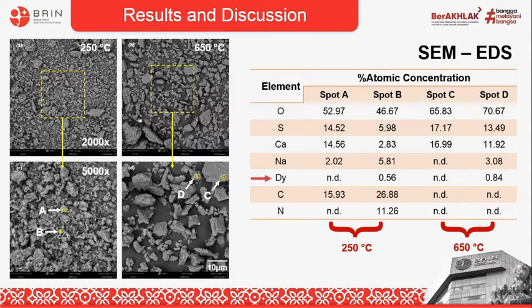The existence of dysprosium was spotted in several regions, indicating the successful introduction of dopant material to the matrix. And the presence of carbon after heating at 250 Celsius degree indicated the interaction between ethanol and other molecules of compounds used in the synthesis route, likewise the ammonia, denoted by the presence of nitrogen. The compounds containing carbon and nitrogen were found to decompose as the temperature increased along the calcination process, since both elements were detected only in the 250 Celsius degree samples.